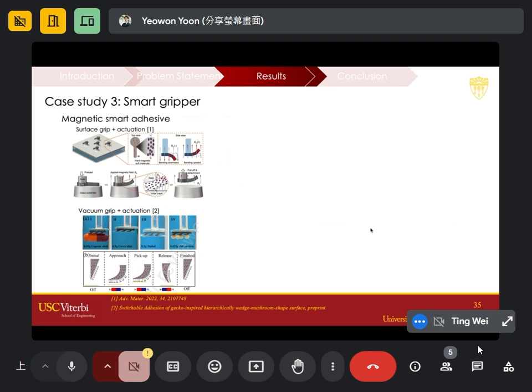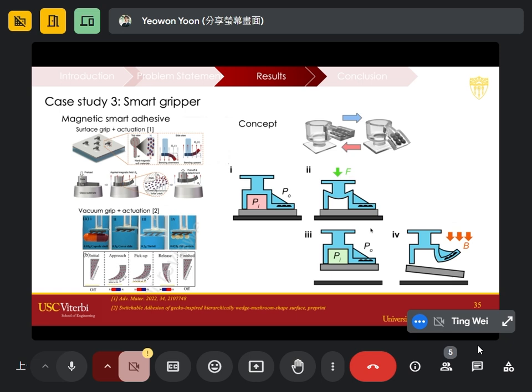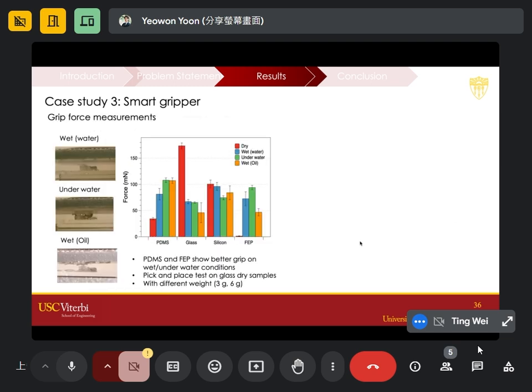So we came up with this idea about using this as a suction cup, but one that can selectively choose and release a substrate. If we have a cup that pushes in and creates a negative pressure inside, it's just like a suction cup in your bathroom, you just push it into the wall. But if you want to take it off, you lift the very boundary point and then apply the actuation. When this happens, the vacuum breaks, and it loses the grip and the adhesion to the substrate.